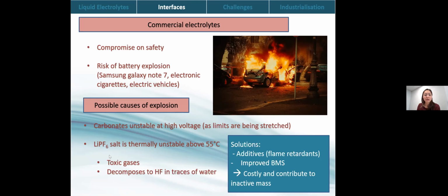And also the LiPF6. Today, when we test the electrolytes, the batteries, we seldom go beyond 40 or 45 degrees when we use LiPF6 or carbonates, because LiPF6 salt is thermally unstable above 55 degrees Celsius. And beyond that, we risk the production of toxic gases, and the PF6 also can decompose to HF in the presence of water. So there are some solutions at the moment, that is adding some flame retardants, additives, or we can use improved BMS to control. But these solutions can be costly and can also contribute to inactive mass within the cell.